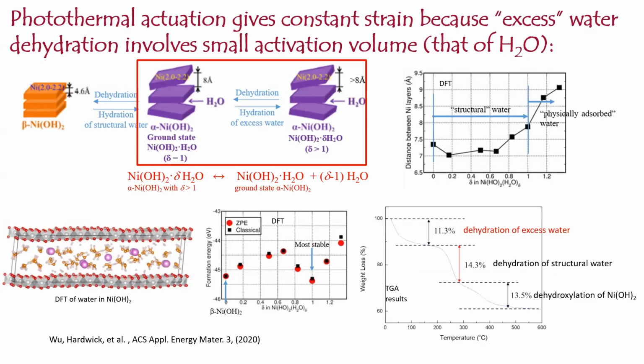Why is it like that? Constant strain. Again, this is due to water removal, a very busy graph, but basically you remove the free water content. So in the turbostratic structure, there are two types of water. One is called structural water, which is hard to remove. They are bound rather tightly to the structure. The other one would be the excess water, which can come out very easily.